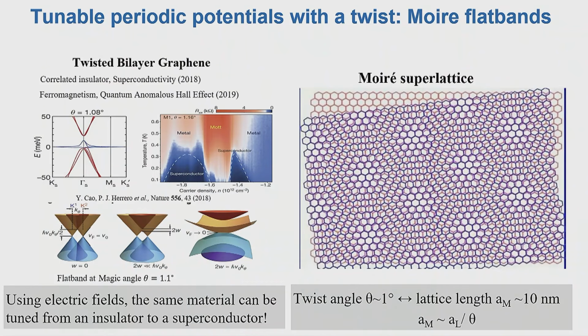And what is remarkable, to me at least, is that when you stack two graphene layers with the finite twist angle, and in this case it has to be precisely 1.1 degree, then you find that even though you started out with massless electrons, you generate a very flat band, meaning that the effective mass of the electrons that you dope into this band is extremely high. And that means that the system will be subject to correlation effects.